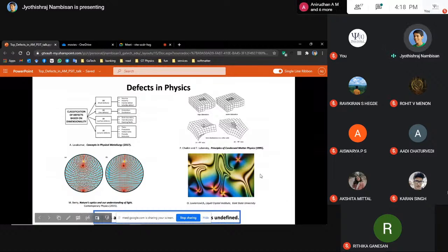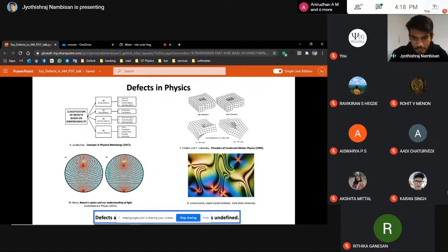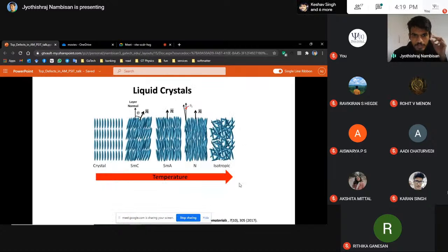Okay. So let's focus on this example here, liquid crystal, because it's very colorful and it's very instructive. Liquid crystals are systems which are literally between liquids and crystals. When you have a crystal, you have your broken symmetries and you have translational order along some axis and also orientational order in some other axis. And as you melt the crystal, either by using temperature or some other control parameter, you end up with an isotropic fluid, which is known as a liquid state, characterized by the absence of any orientational order or positional order. So whichever way you look, the system is isotropic.